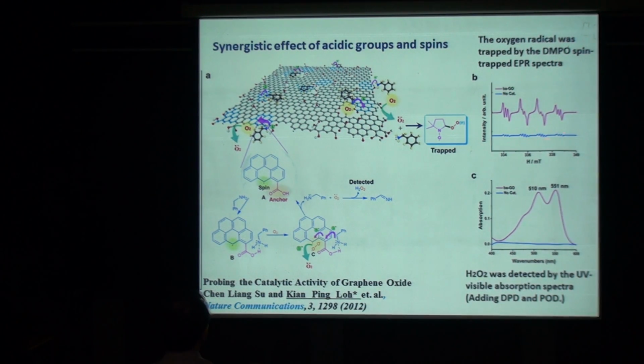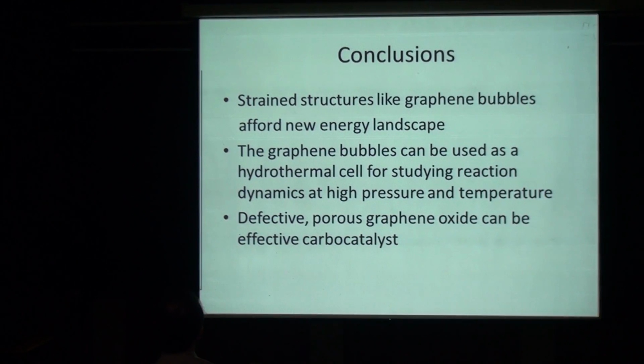If there's no catalyst, you don't see this. Anyway, this just shows you that the synergistic interaction of the acidic group and the spin gives rise to a very high catalytic activity. So the conclusion here is this. Strained structures like graphene bubbles afford a new energy landscape. When you strain the graphene, you change the energy landscape completely, you open up a band gap.